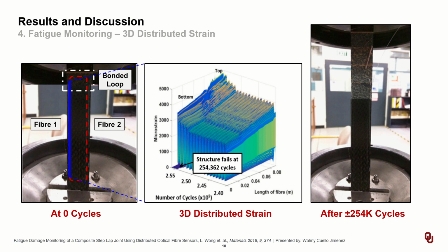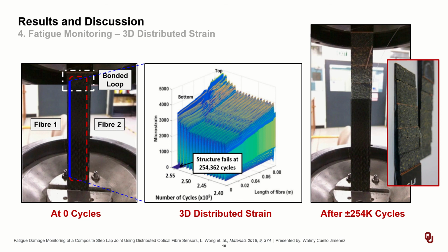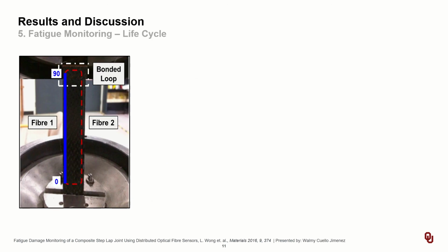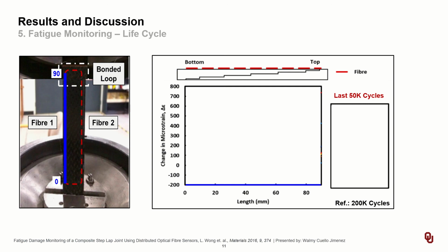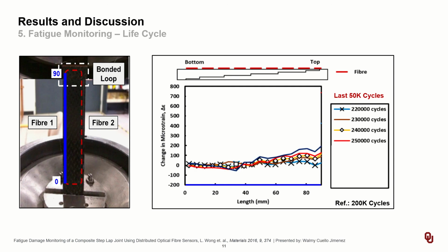Now the photos of the specimen after failure indicate that first, ply failure takes place, followed by net tension and adhesive failure. Lastly, to complement the work, it was necessary to further prove the ability of the system to measure the life cycle of the specimen. This was accomplished by focusing on the last 50,000 cycles, using the 200,000 cycles strain measurements as a reference. Results from strain measurements across fiber 1 from 0 to 90 millimeters, the bonded area, indicate that